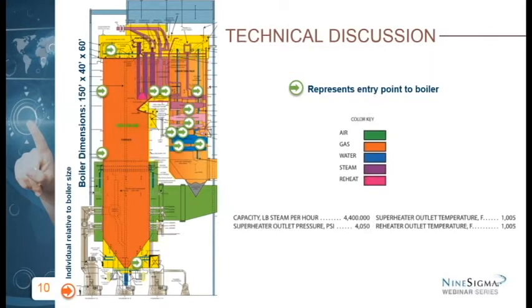But as we get up into those, it's the pinkish section, that's what we call our superheat section, and those tubes are just hanging from the roof of the boiler. And if one of those ruptures, it typically starts to swing around almost like a fire hose, and can do a lot of damage up in that section, and turn those pendant tubes into what looks like spaghetti sometimes. And that requires a lot more work.